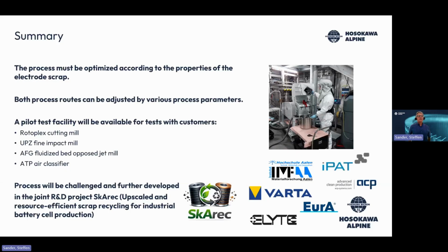You will always have a source of ignition. So you always have like three options. You can try to have a protective system by not having an ignition, and if you have, let's say, rotors running with high speed, you can never say that you have no source of ignition. That's for sure. But then you could run this process, and in some cases this might also be necessary to protect the material itself from oxidation or other detrimental effects. It might be necessary to run under inert atmosphere.